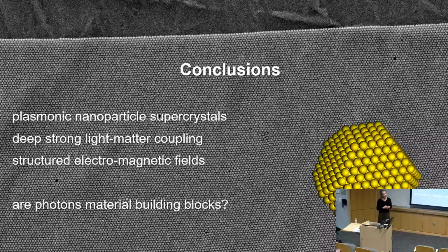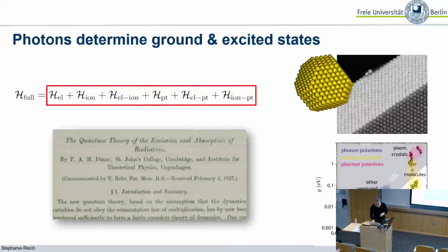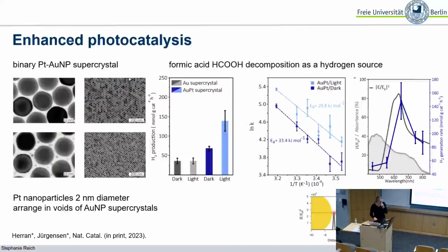Yeah, second question about the HER catalysis. So it's really plasmonic. The platinum quality compared to gold, platinum clearly seems like the catalyst part. It's really hard to control that part. I wonder, is that light enhanced? It's really a trapping of protons. You do use formic acid, right? With formic acid, you have a lot of protons there. With light, with polaron formation, you have a negative charge that can attract a lot of protons. So the local concentration is going to be higher, and then you're going to see the enhancement. Do you think it's just a chemical effect, or is it a light effect?